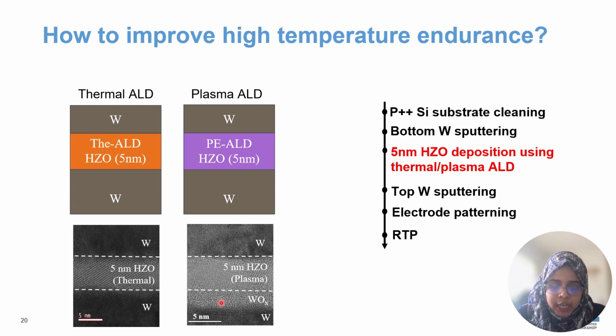Now, if we look into the TEM of both devices, we can see that we are able to get a 5 nanometer HZO film sandwiched between the top and bottom electrode. But what's different is that in the plasma ALD film, we are getting some unintentional tungsten oxide layer at the bottom interface, because the plasma ALD process is a high power process. So while depositing the HZO layer, we are unintentionally oxidizing some portion of the bottom tungsten electrode.